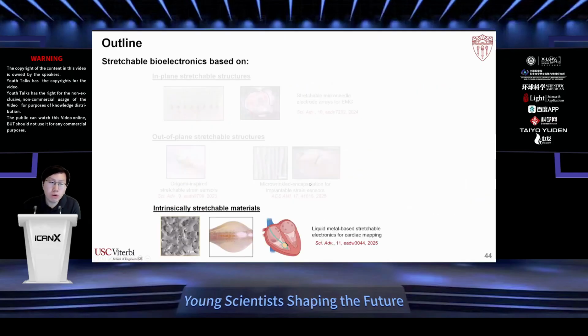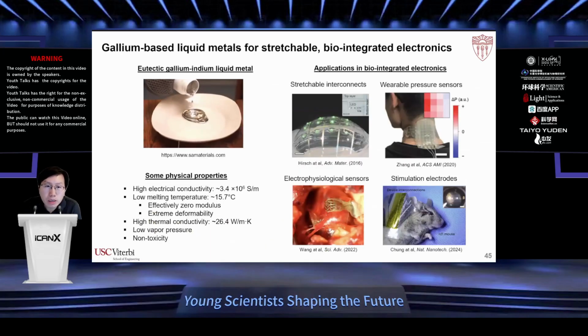And then the third example, I'm going to show that we can use intrinsically stretchable materials for making stretchable electronics, in this case with gallium-based liquid metal. Gallium-based liquid metal, especially the eutectic gallium indium liquid metal, has been a very promising material for stretchable electronics because it has metallic-level electrical conductivity, and it's fluid at room temperature, so it has extreme deformability, effectively zero modulus, and has high thermal conductivity, low vapor pressure, almost doesn't evaporate, and is not toxic. So because of these reasons, this eutectic gallium indium liquid metal has been used for different purposes in stretchable electronics.